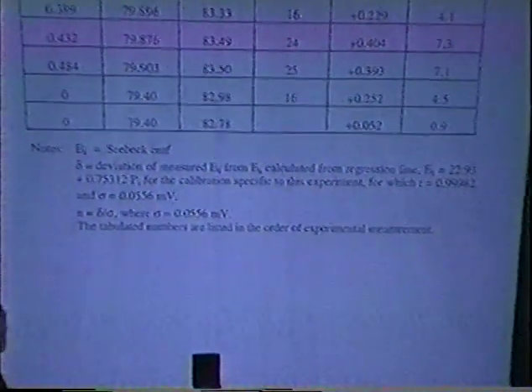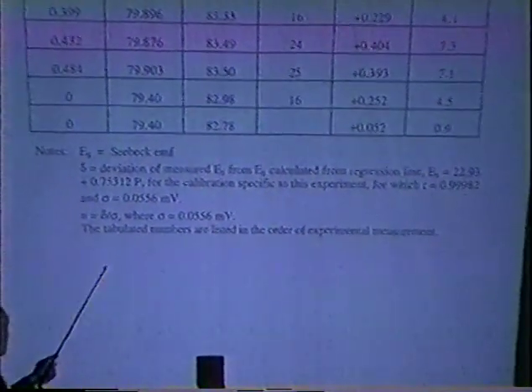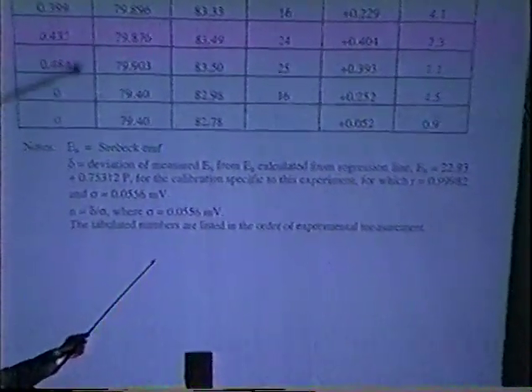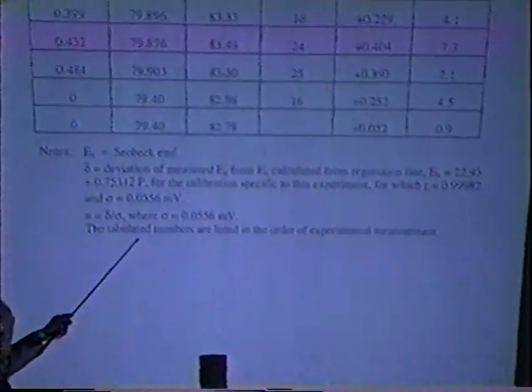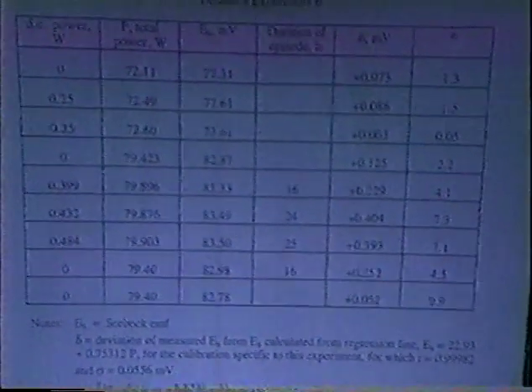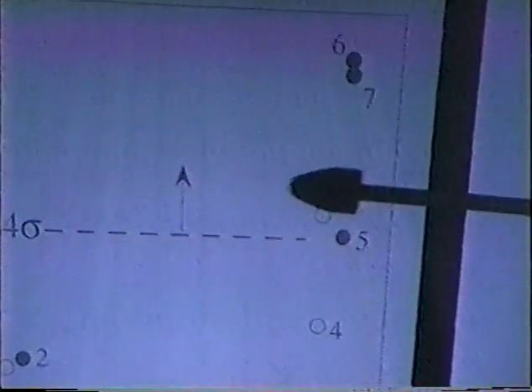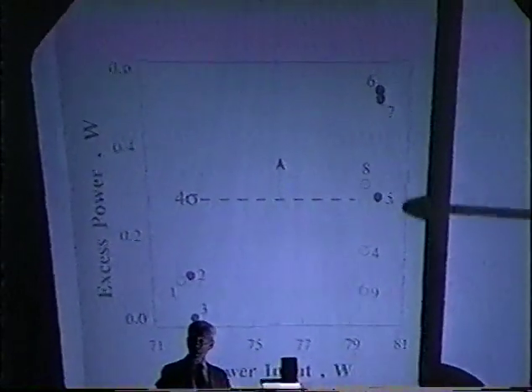Using the same specimen and another kind of calibration and then power runs, I have these results. Again, the same kind of tabulation. The last 2 columns give you the deviation in millivolts and the number of sigma values from the regression line for the calibration. And in this case, we had as high as 7.3 sigma values. And again, I can make that same kind of plot as I showed you before. All values above 4 sigma, I can be very confident are in fact excess power.